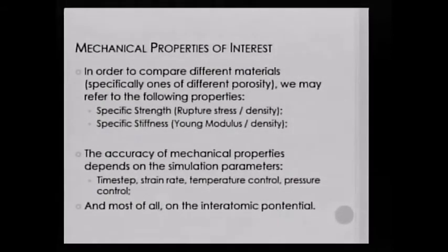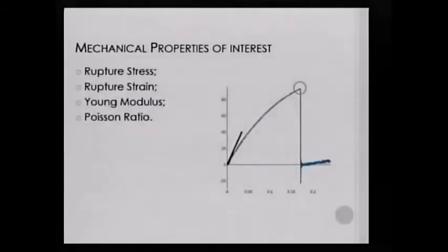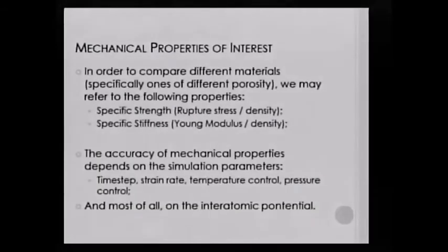Besides that, I also want to point out that the accuracy of the mechanical properties we obtain from this curve depends on the simulation parameters. That includes the time step, the strain rate, temperature control, pressure control, and most of all, the interatomic potential. This is something we're going to talk a little bit more about in the LAMMPS session today, about how this can affect the quality of the results, as you all saw in Professor Andre's talk yesterday.